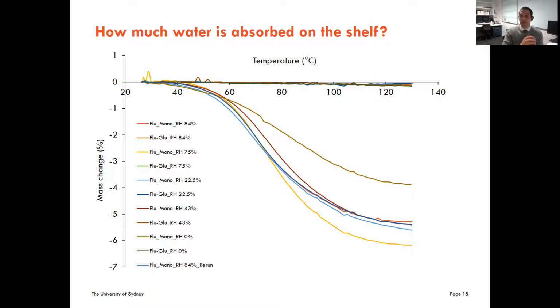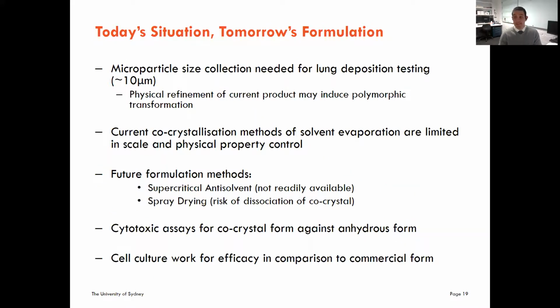This one's going to keep the co-crystal for a much longer period at almost 84% relative humidity going forward, which is obviously quite a considerable amount. But again, we can have high amounts in the manufacturing process along the factory line. This is a great application in terms of providing that stability and structure going forward to slow down any degradation, but also polymorphic transformation that can cause a bit of trouble. So that's today's situation. That's where we've got to so far in my research.